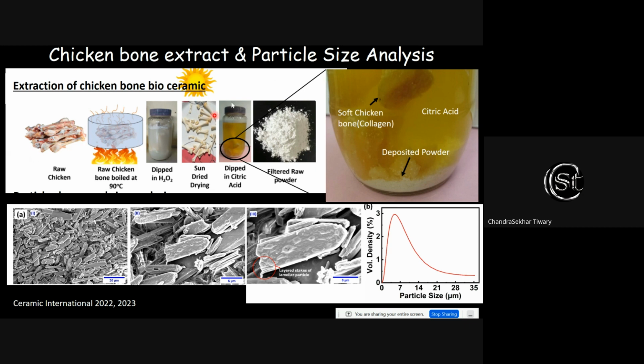Now, we take the chicken bone and do a very green chemical treatment. We clean it up first, put it into citric acid, and let it be there. When you let it be there for a long time, if you get the right chemistry, you can make a nice fine powder out of chicken bone. Now, again, there are a lot of methods where people try to crush it, but the problem when you do ball milling and all, you end up modifying the shape, you may end up contaminating, and all sorts of problems can come. But with this non-destructive method, where we don't put any energy, just by chemical treatment, you can extract this powder. It can be easily scaled up depending on your reactor. You can make it as large as possible.